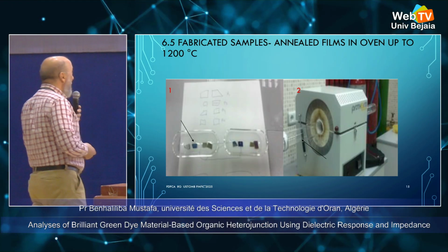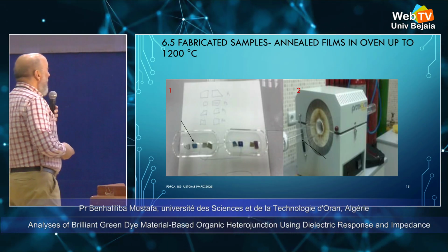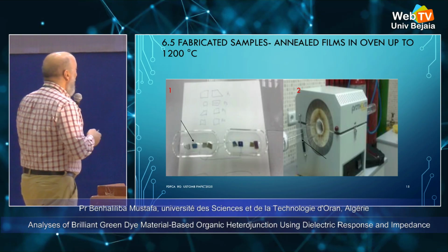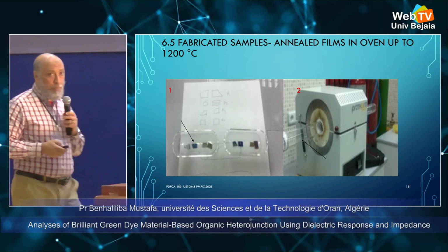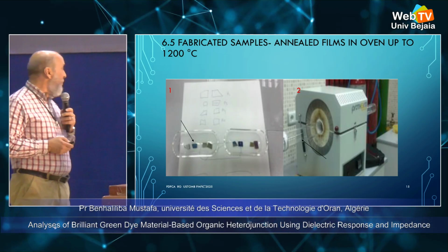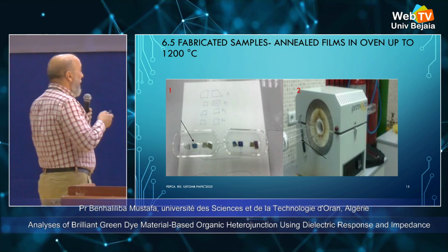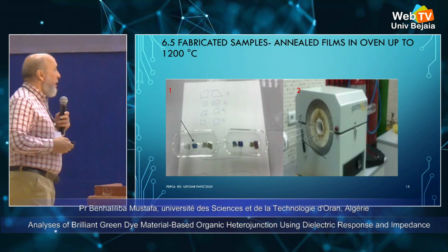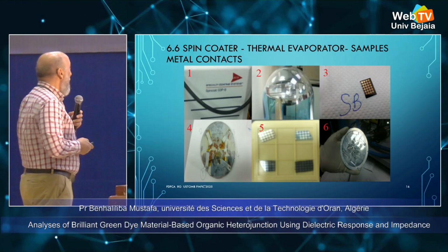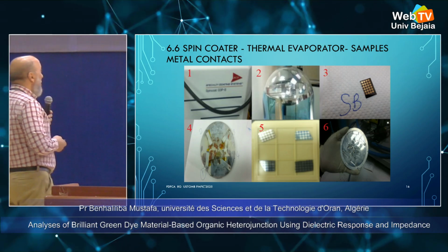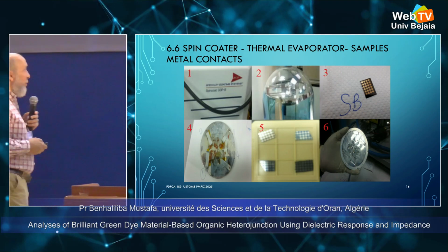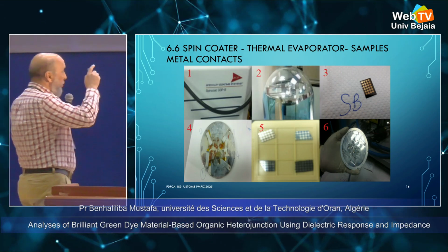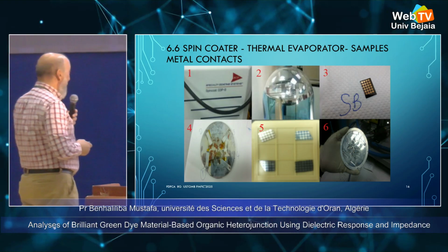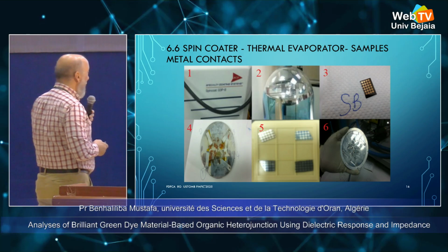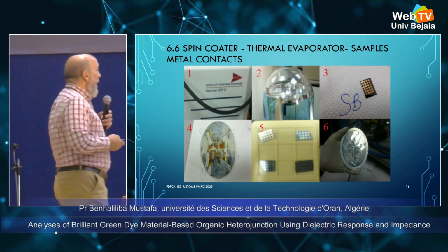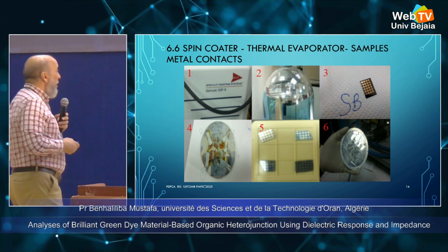In this figure, we have fabricated samples. In figure 1, we put the sample in a crystal glass boat. Sometimes we use alumina boats. In figure 2, we put them in the tubular cylinder and put it in the furnace. In this figure, we can explain the spin coater in 1, and in 2, the thermal evaporator. In 3, we have the gold contact, displayed as dots of gold. In 4, we have also the substrate holder and the substrate after evaporation. In 5 and 6, we have some other contacts in aluminum.